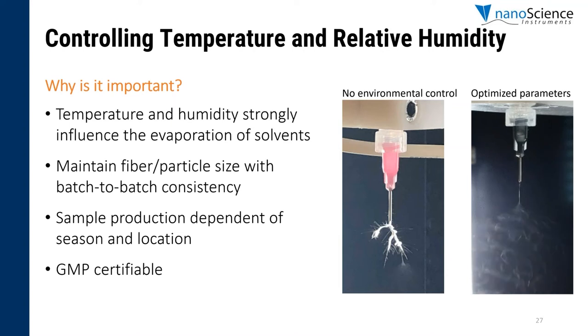When not controlled, you can have fast solvent evaporation, making the polymer partially solidified at the emitter and secondary jetting happening simultaneously. That is obviously the image on the left. But then when all parameters are well controlled and optimized, you get the beautiful electrospinning process shown in the right image, causing reproducible and consistent sample production over time.